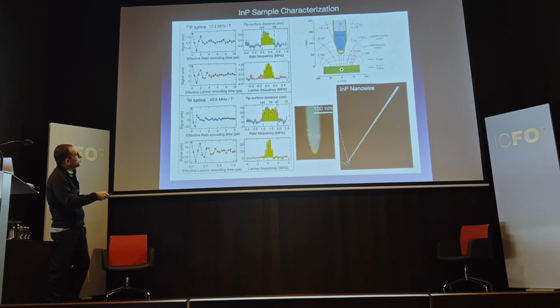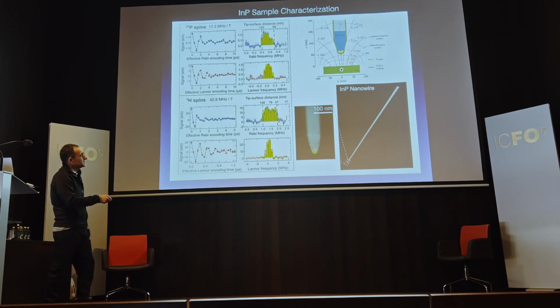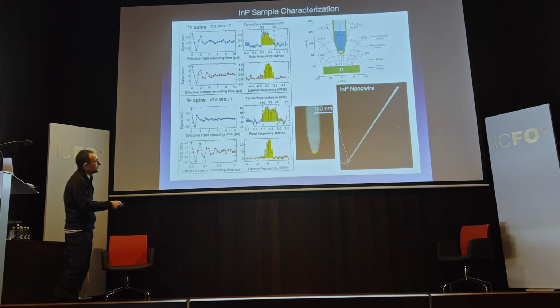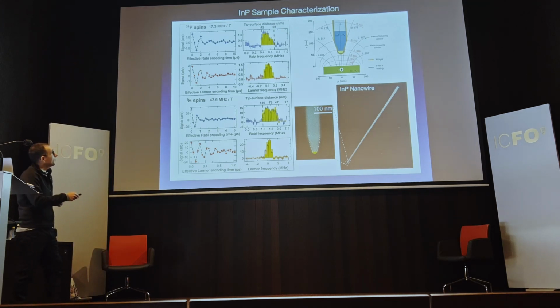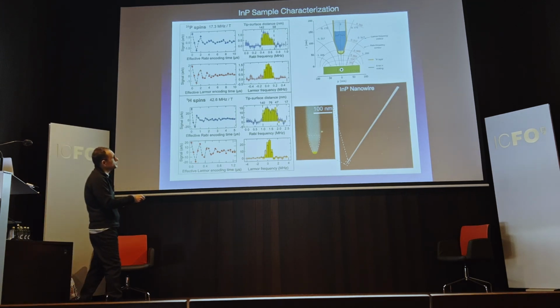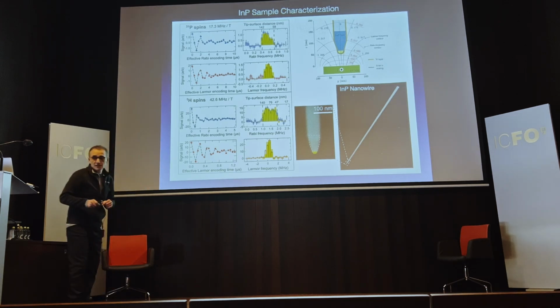And then we match them up with the theory for what we expect for that conical tip. This is a 20 nanometer gold catalyst particle. The volume that we study is about 80 nanometers tall. This is about 60 nanometers across at the top here. Okay? We imaged both the proton spins on the surface, that's this. There's about a 2 nanometer layer of water, and the phosphorus spins as well.